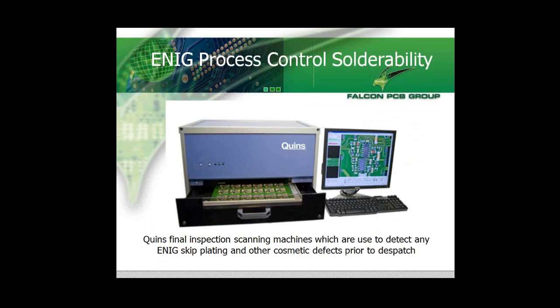On the final slide, what we find is the odd problem that's always one of our sort of worries tends to be the odd skip pad or odd couple of skip pads, etc. So what we do at final inspection, we utilise the Quins scanning system to actually detect any of those. What it does is we have an image from a perfect board, and then we scan all against it. Any discoloration is found immediately and highlighted, and hopefully we can make sure that there are none of those ever go to the customer.